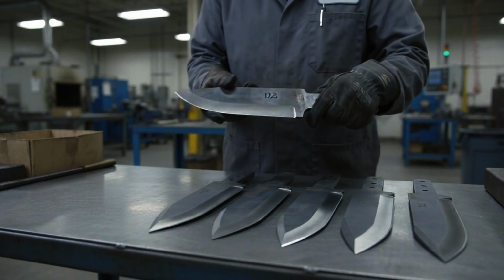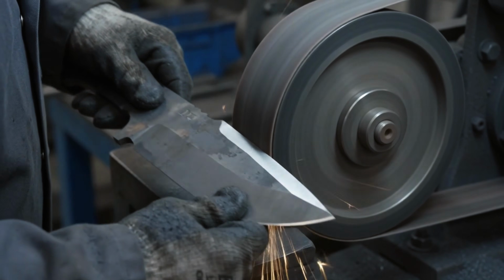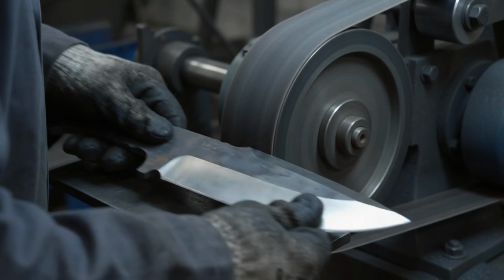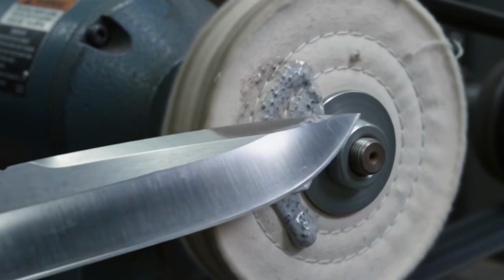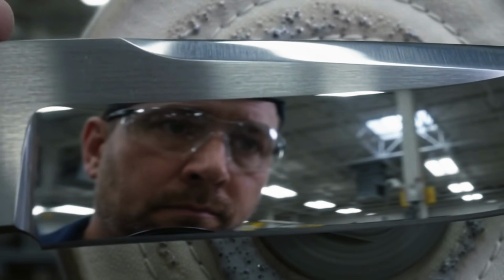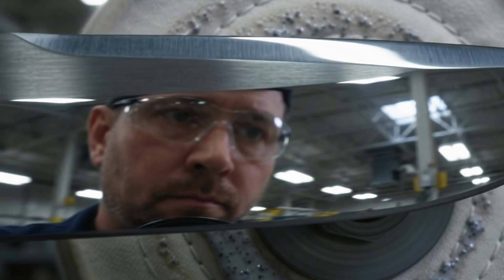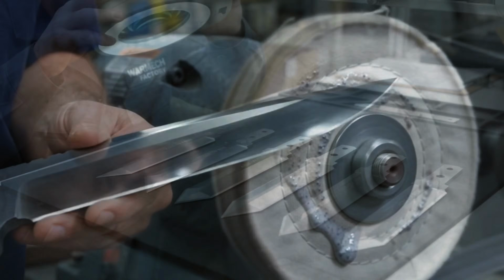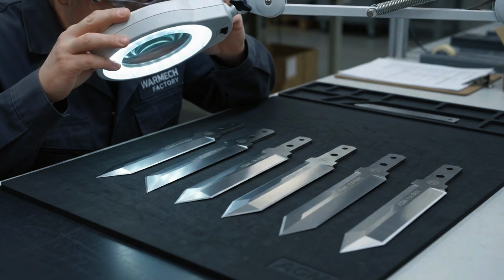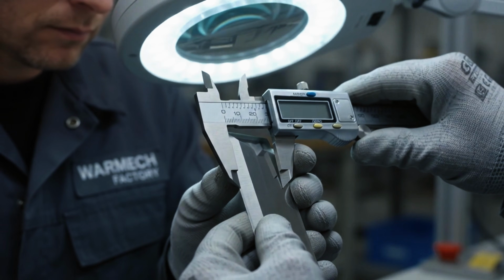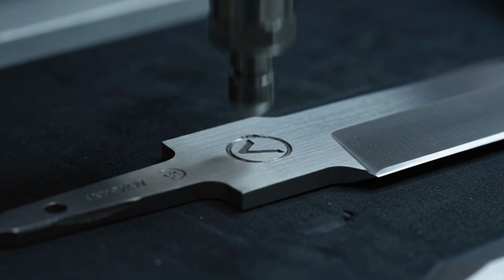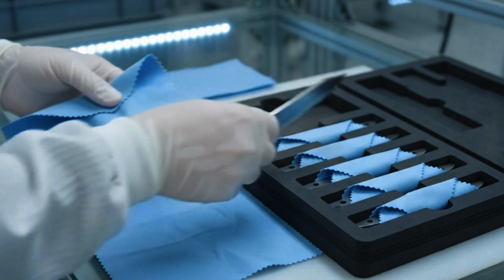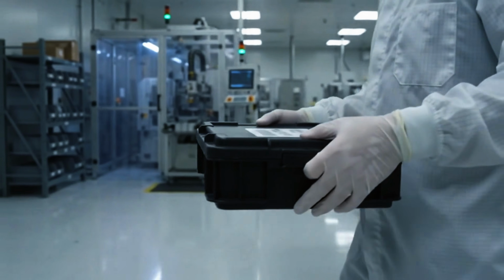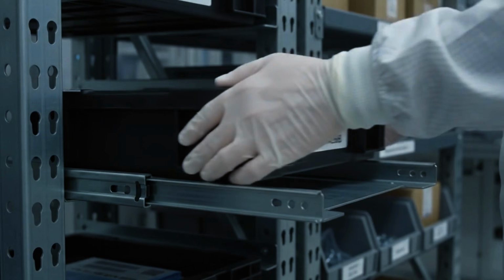the R9X blades enter the multi-stage polishing process, progressing through 220, 800, and 1200 grit stages. The final mirror polish brings each R9X blade to its finished state. This mirror surface is a signature of this weapon system. 6 completed high-carbon D2 steel deployable razor blades, each mirror precision ground and hardened to 60 HRC. The 6 deployable razor blades are individually protected and stored in a dedicated parts tray.